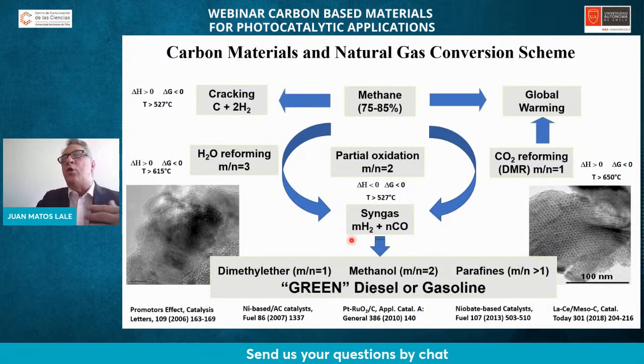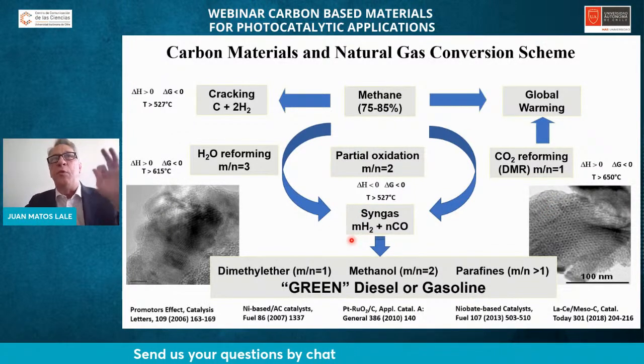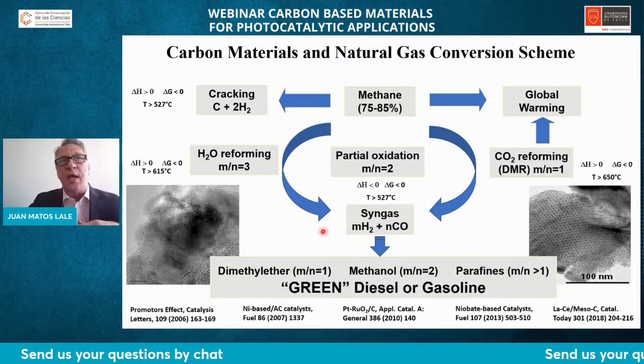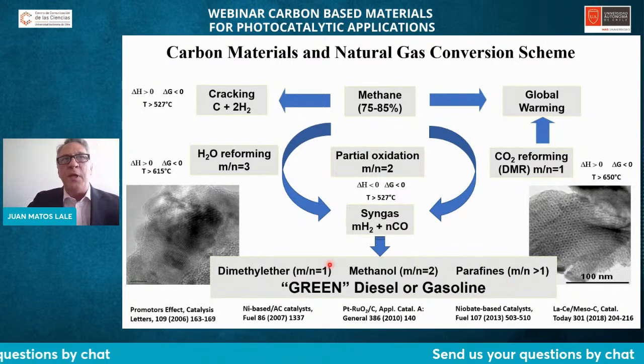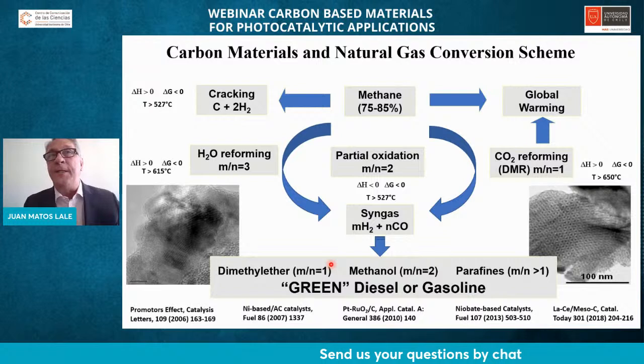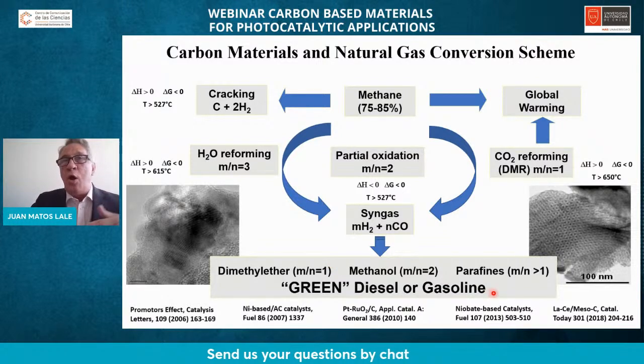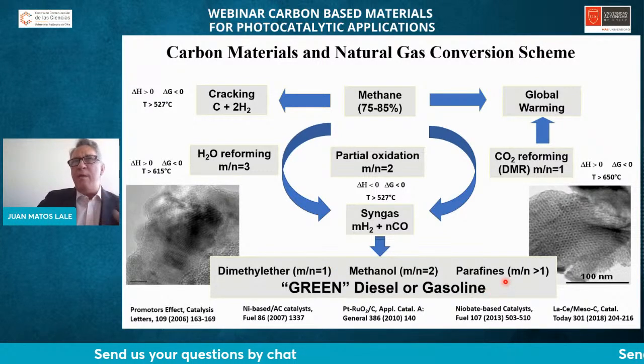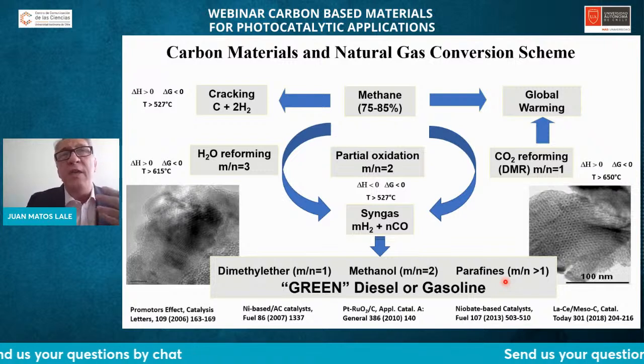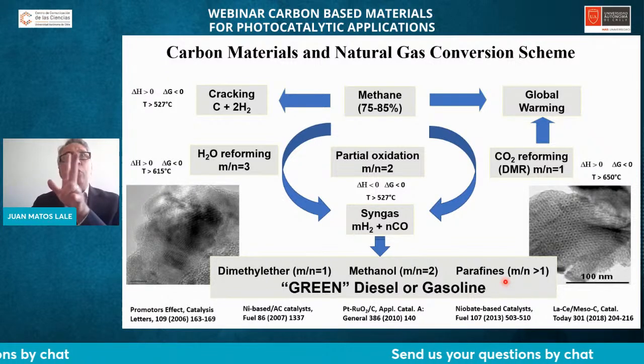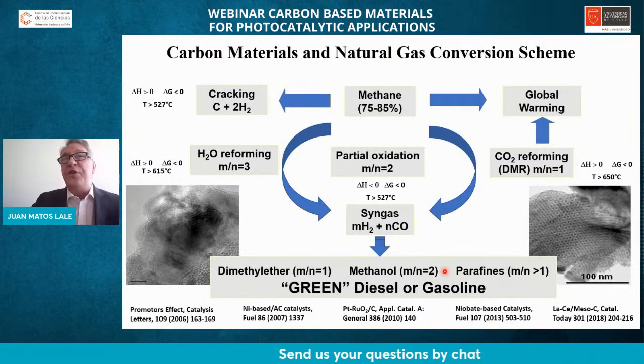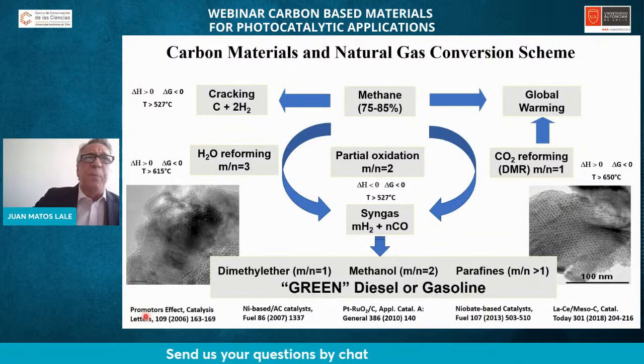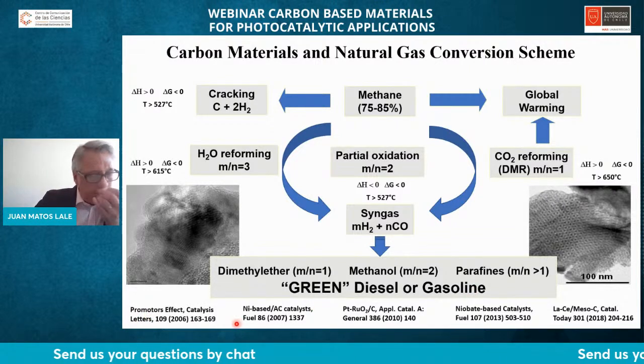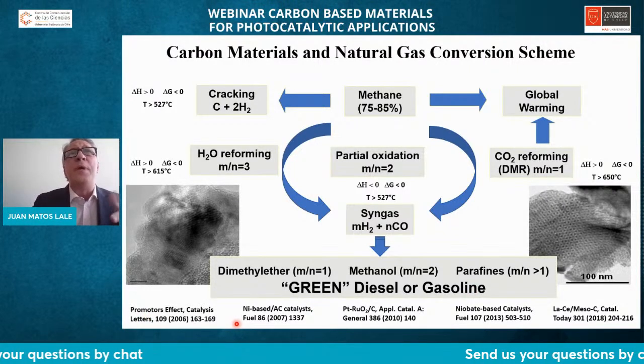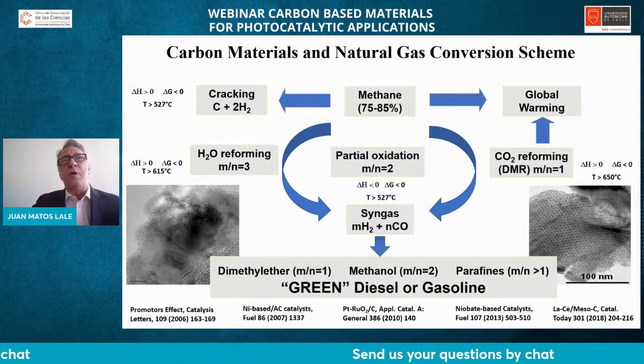Depending on the stoichiometric relations between the hydrogen and carbon monoxide, you are able to produce dimethyl ether, which is a very important additive in gasolines, methanol, or even paraffins. We are able to arrive even to produce hydrocarbons this way, by Fischer-Tropsch synthesis. We have published different kinds of studies around carbon-based materials in hydrogen production.